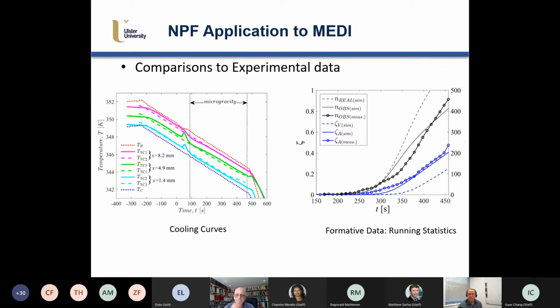So to show you some of the results, the microstructure kinetics drives the latent heat evolution in the sample. So you see here the thermal agreement. We're able to get quite good agreement here with the measured cooling curves. Looking on the right, some of the running statistics that we were able to develop and observe from the experiment itself and what we were able to model. So looking here at the black, you have the number of nuclei observed in 2D, and the number predicted by the model. Observed in 2D is these dots, these circles, and then the black line is what was actually simulated.